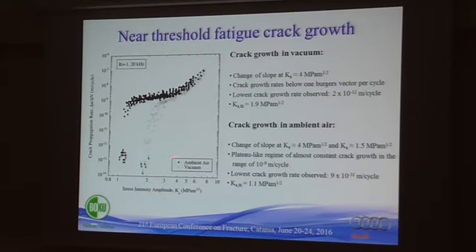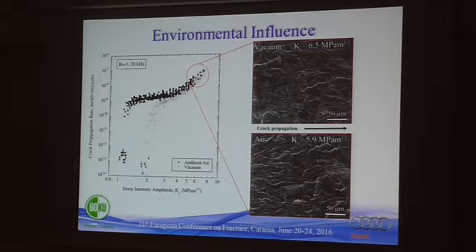Also remarkable are these very low crack growth rates that can be observed in vacuum, which are below 1 Burgers vector per cycle. So, since we find a very strong indication for stress corrosion cracking in the crack growth curve, we also expect to find some or more evidence for stress corrosion cracking on the fracture surface. And we performed some fractographic investigations, and here the fracture surface in the regime of very high fatigue crack growth rates where environmental influences are suppressed due to very high testing frequency. We find indeed that both fracture surfaces seem to be similar, displaying a rather smooth and featureless fracture surface.